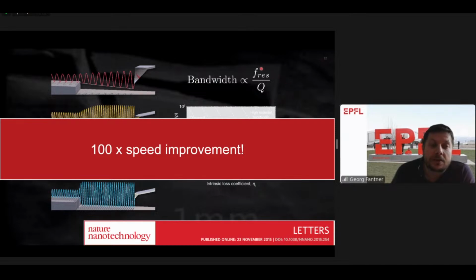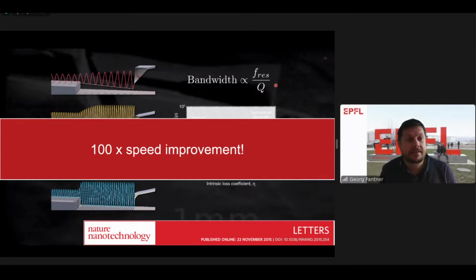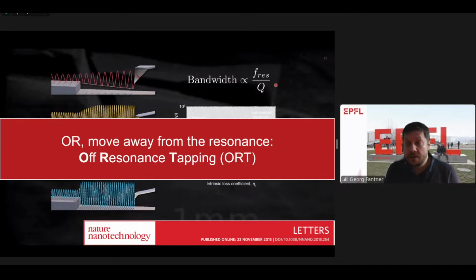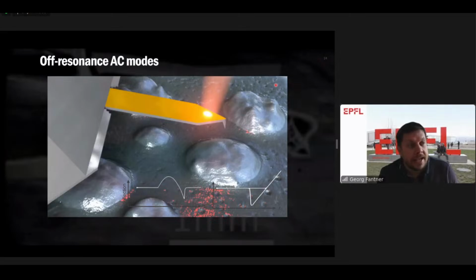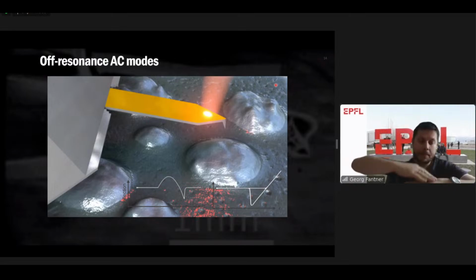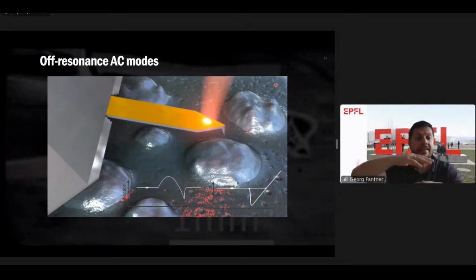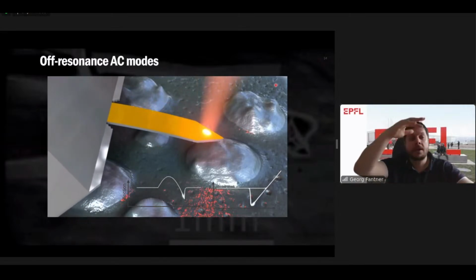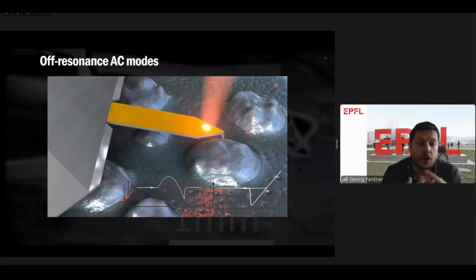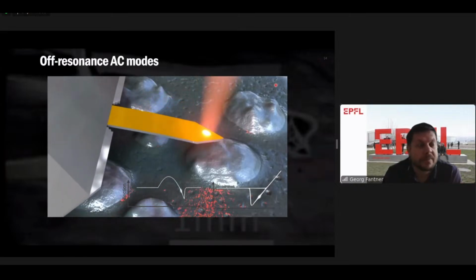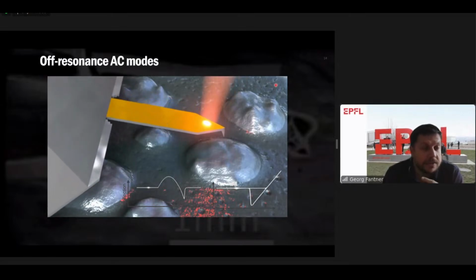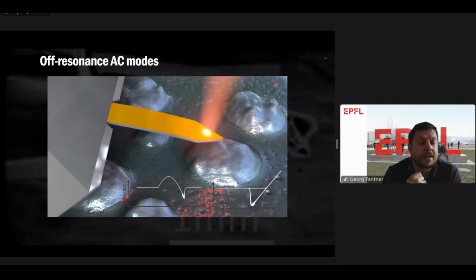This bandwidth equation here is valid for when you are exciting the cantilever at its resonance, when the oscillator is resonating. But what happens if we use the cantilever not at its resonance frequency, but at a frequency far away from the resonance frequency? Well, that is what we call off-resonance tapping. In off-resonance tapping, instead of shaking the cantilever at its resonance frequency, we are actually moving it up and down in a controlled fashion and touching the sample, coming back up, and retracting it. And we do that for every pixel at least one time. The frequency with which we do this is generally much, much lower than the resonance frequency.